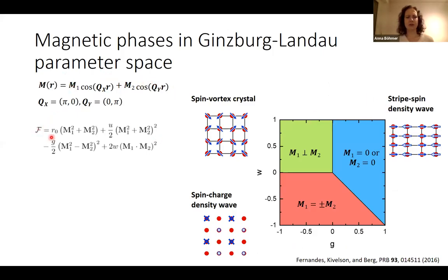But in the Ginzburg-Landau approach, there are different coupling parameters, and in the phase space of these coupling parameters, we find different magnetic orders as well. There is this spin vortex crystal magnetic order, where the two order parameters are perpendicular to each other. And that's where the non-collinearity comes from. There's another one where they are parallel and of equal size. That's called a spin charge density wave, or C4 by some experimentalists. But today we are going to talk about this area here.